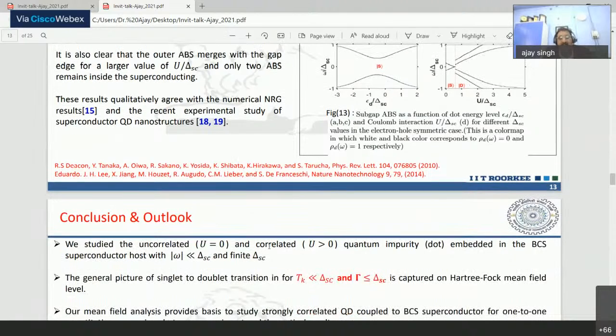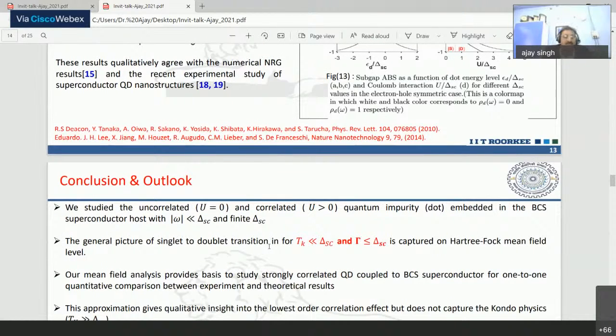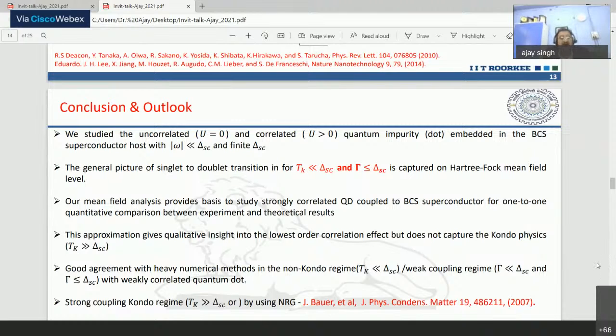So if I just put a summary of the work which we have done, in the U tending to 0 and U non-zero regime, the quantum impurity embedded behaves differently if you are in the bound state regime, and if delta is finite, then there is a singlet doublet transition, which is actually beyond the Kondo effect that is seen when the Kondo energy scale is smaller than the superconducting order parameter. So this is the regime where we are going away from the Kondo effect, and it basically supports a doublet phase.